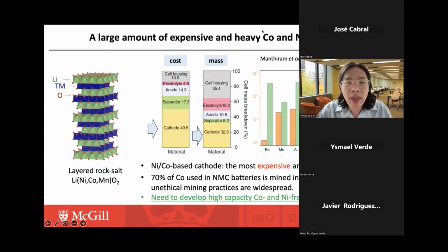For example, if you look at the materials cost, there are in total about 6 to 7 components in the lithium-ion batteries, and the cathode alone takes over nearly 50% of the total material cost. And because cobalt and nickel are heavy species, the cathode also takes over nearly 33% of the total mass of the lithium-ion battery. Therefore, considering all this, the performance as well as the cost of the lithium-ion battery is largely determined by the cathode material.